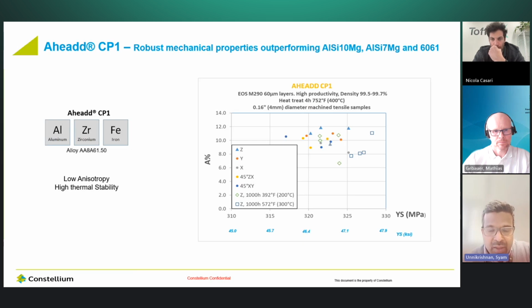And also, if the material is exposed to high temperatures, such as 200 degrees Celsius or 300 degrees Celsius for a long duration, let us say 4,000 hours, as we can see in the graph, the material never changes its microstructure. So if you cool down and test the material, you will see similar properties coming back. What it reflects on a component level application is that the durability of the component goes for quite a long time compared to other aluminum alloy systems.